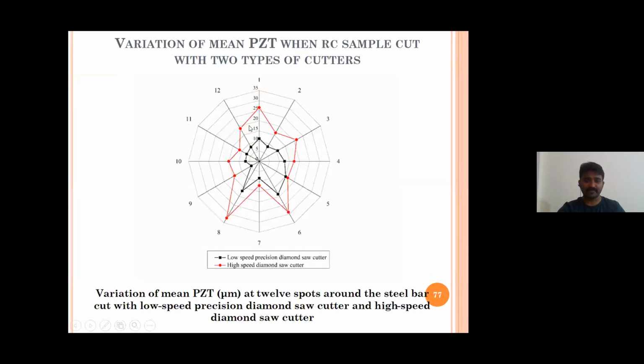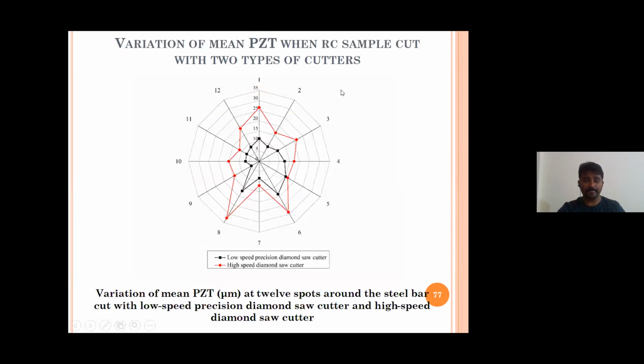If you could remember the SEM images that we have measured previously, these are mean values of porous thickness at 12 spots. These are the mean values, and these are the standard deviation, minimum value and maximum values. So with the mean value plots, we try to understand what is the effect of cutting tool, high speed cutters and low speed cutters, on porous thickness. If I use a high speed diamond saw cutter, see the red portion at these spots, spot 1, spot 2, likewise there are 12 spots.